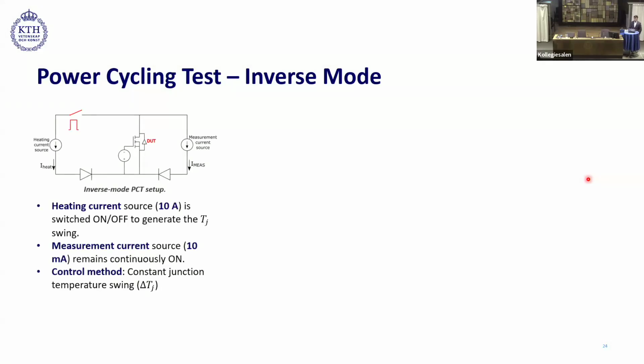First, we started with inverse mode power cycling test. In the inverse mode power cycling test, body diode is used for generating heat, and the DUT, the device under test, which is basically silicon carbide MOSFET, is always kept in an off state in order to ensure that the MOS channel is completely off. The heating current source is turned on and off for providing the heating and then cooling. Here we have a measurement current source, which is always kept in an on state. We used 10 amps of heating current and 10 milliamps of measurement current. The control strategy that we used in this test was constant junction temperature swing, that is constant delta T.